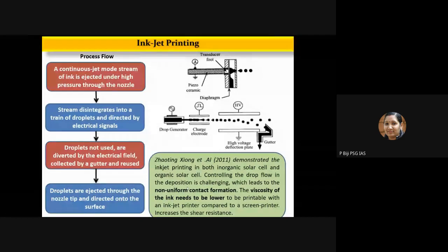The first one is inkjet printing. Most of you must be familiar with inkjet printing. In this particular technology, if you see the process flow, there is a continuous jet mode stream of ink, which is injected under high pressure through the nozzle. This stream disintegrates into a train of droplets, which is directed by electrical signals. The droplets which are not used will be diverted by the electric field and collected by a gutter, and can be reused. The droplets which are ejected through the nozzle tip are directed onto the surface using a piezo drive, and you can actually have XYZ movement, using which you can print the desired metallization pattern on the silicon solar cell.